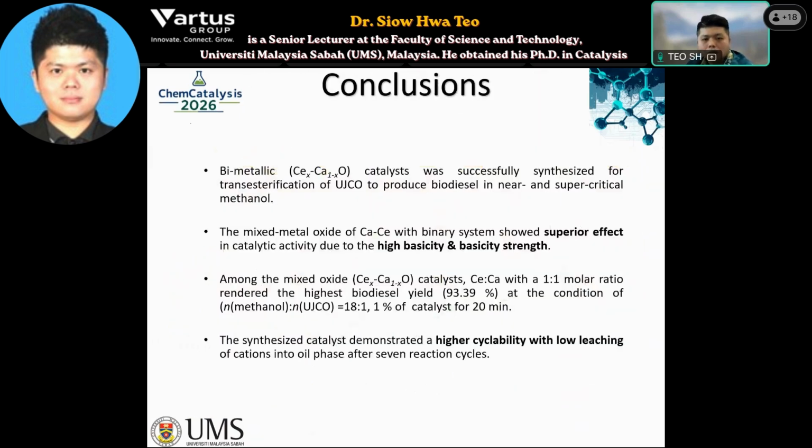To conclude, a series of cerium oxide, calcium oxide mixed metal catalysts were successfully synthesized and evaluated for biodiesel production from unrefined Jatropha crude oil (UJCO) under the near critical methanol condition. The incorporation of mixed metal oxide generated a synergistic effect that enhanced the catalyst stability and catalyst performance among the synthesized catalysts.